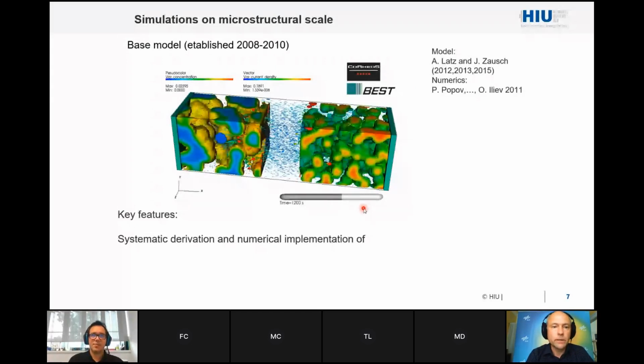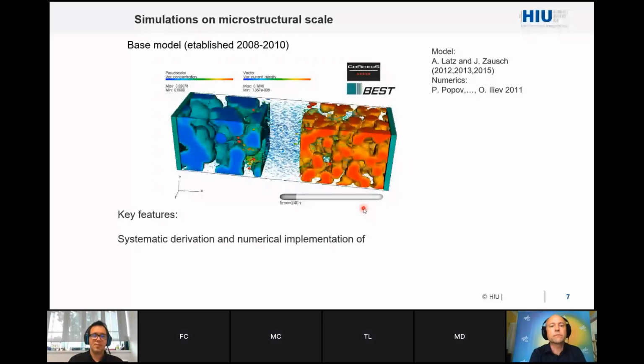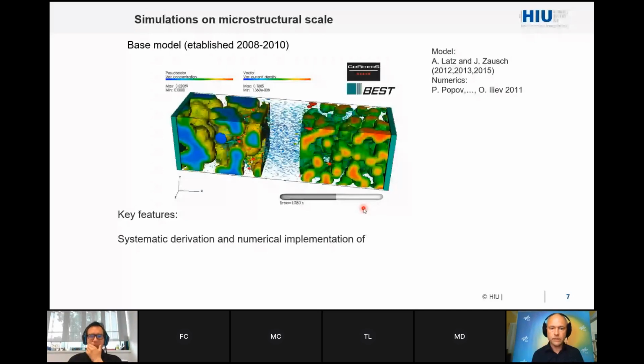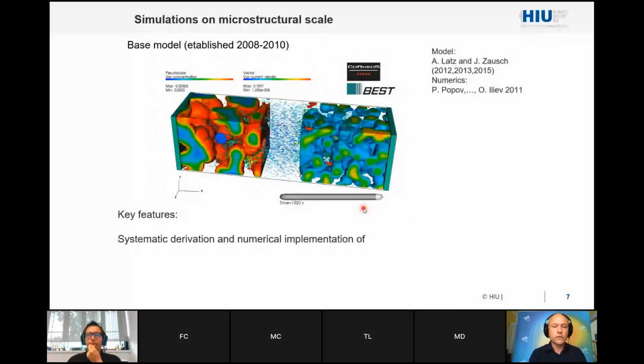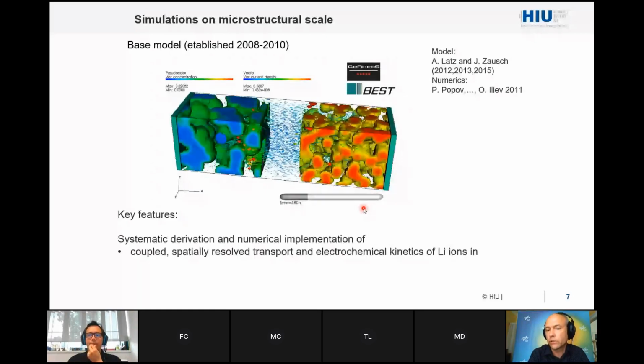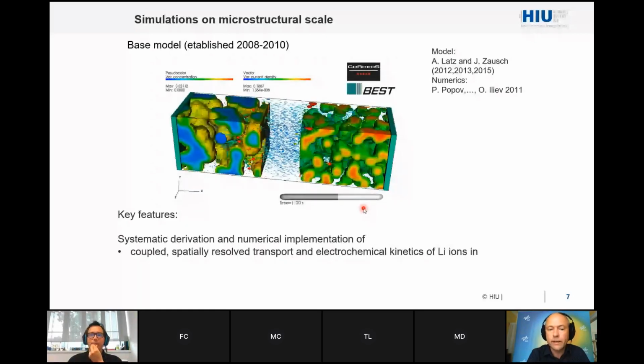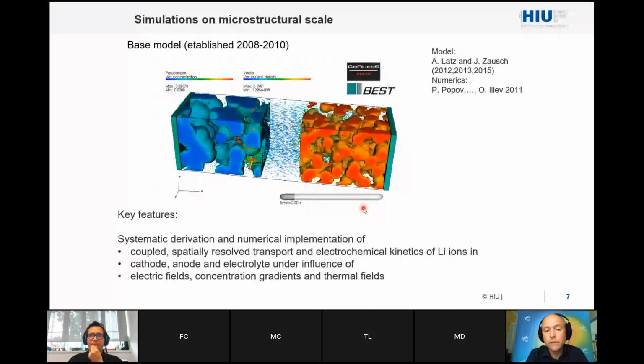This is the software BEST, which I actually developed nearly 12 years ago with my group at Fraunhofer at that time. It's a microstructural modeling approach which we developed together with Jochen Zausch of Fraunhofer from 2010 until 2015. The key features are that it's based on systematic derivation and numerical implementation of coupled, spatially resolved transport and electrochemical kinetics of lithium ions in cathode, anode, and electrolyte under the influence of electric fields, concentration fields, and temperature gradients. This was the base model.